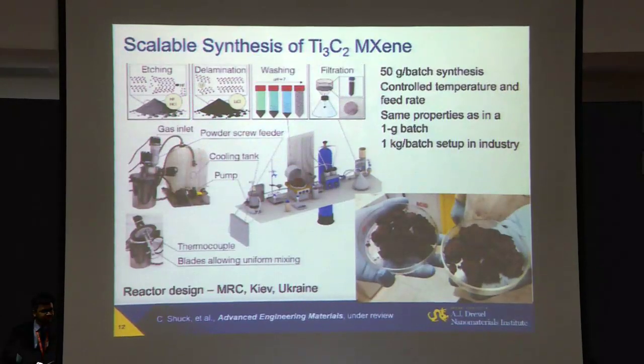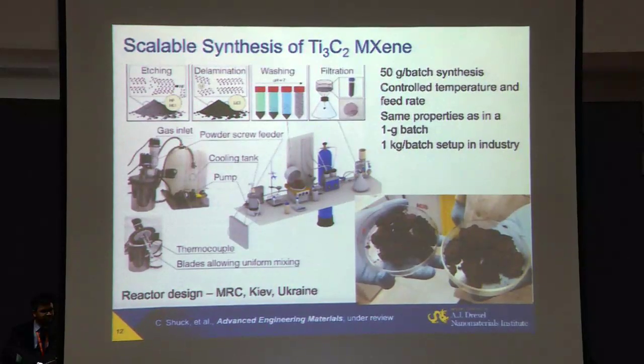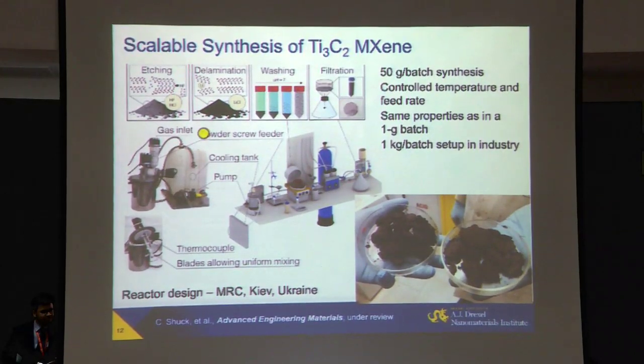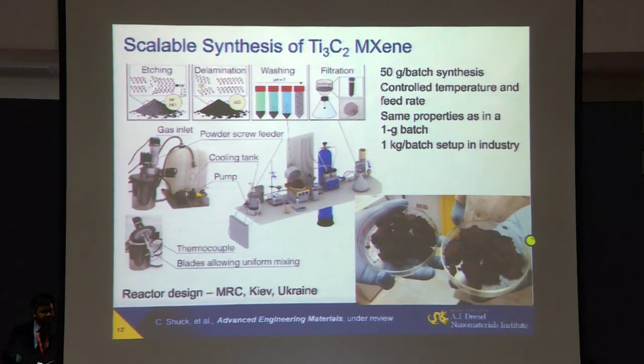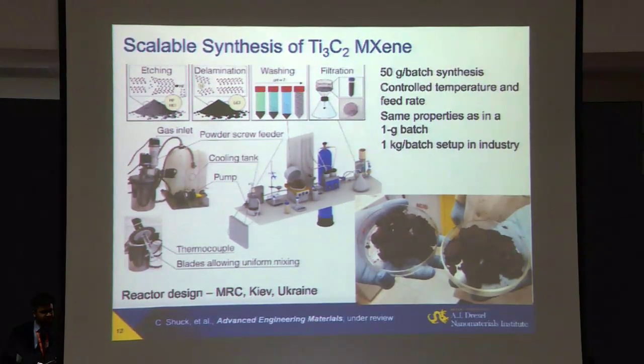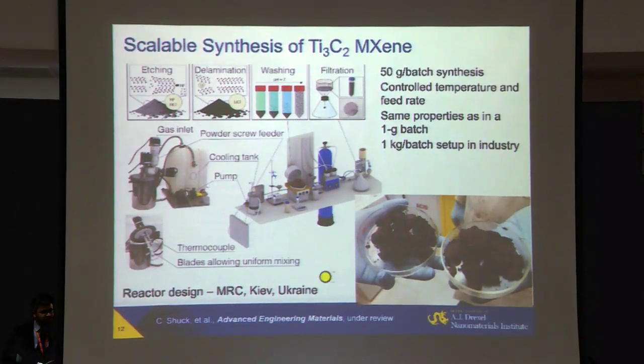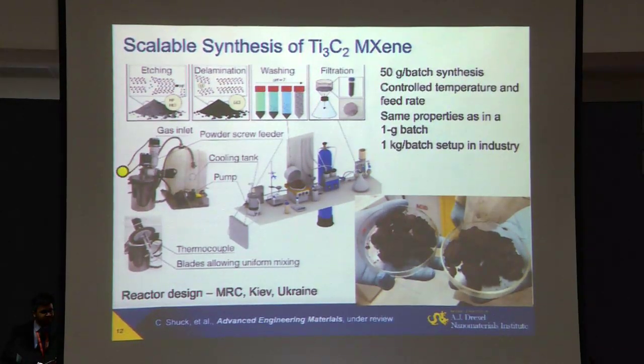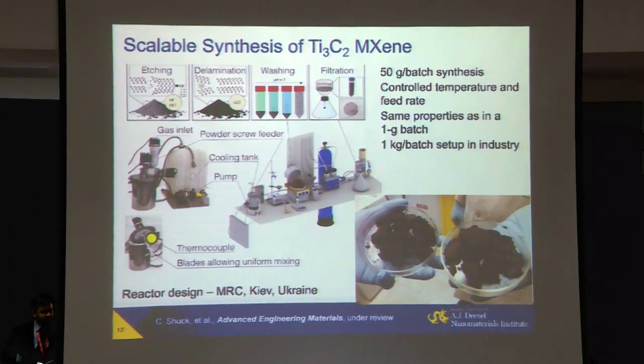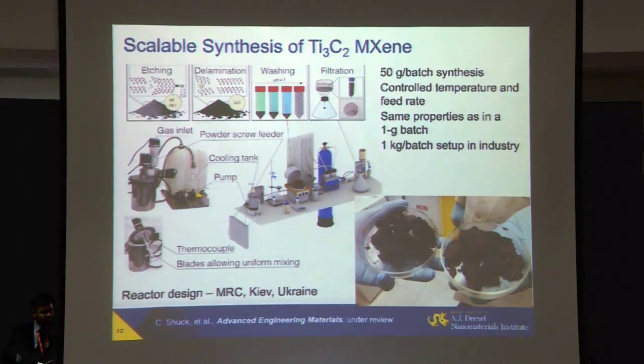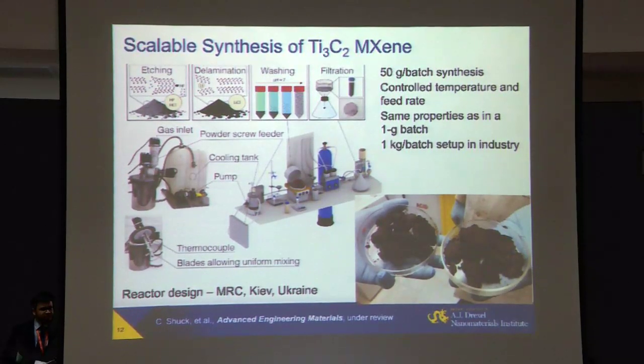But because of this, we actually can produce large amounts of materials. So what you see here, dark brown, it's not chocolate. This is MXene produced from a single etching in a reactor, which was designed by us, by Materials Research Center, and produced in Kyiv, Ukraine. We have 1 liter, and they also made 2 liter reactors. And what it means is that you can make 100 gram of two-dimensional material.